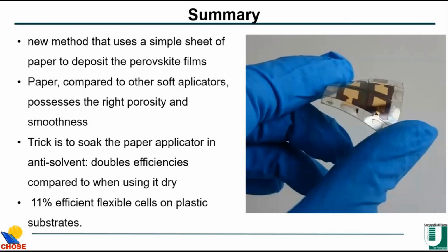And so in summary, I've shown a new method that uses a simple sheet of paper to deposit the perovskite film. Paper compared to other soft applicators possesses the right porosity and smoothness. The trick is to soak the paper applicator in anti-solvent. 11% efficient cells can be obtained.